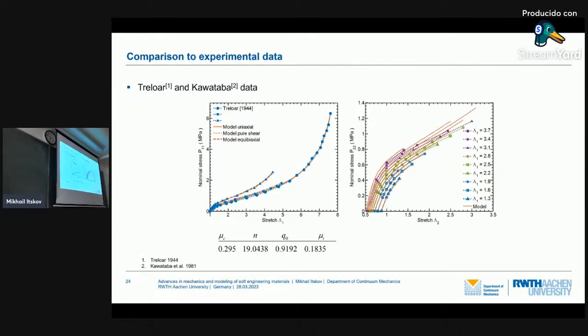So we have all four material constants, and you see here we compare our model with classical Treloar data and Kawabata data. In this Kawabata experiment, biaxial tension was applied with different relations between stretches. So in two directions, we see different stretches. And using only these four material constants, we can describe these two experimental data sets simultaneously very nicely, right?